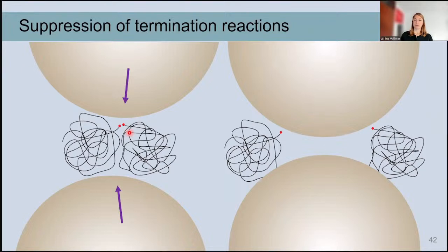And as I said before, we can also stabilize these radicals further with the activation of the surface of the grinding spheres, and thereby promote the monomer formation even further. An alternative explanation could, of course, be that we actually have a different temperature than we measured in the system, which would also increase the depolymerization rate over the termination rate. And when we calculated that, we found that instead of the 40 degrees, we could calculate 140 degrees, and this would then also explain our observed kinetics. But I just wanted to demonstrate that this gives us nice tools to study what is happening in the ball mill.